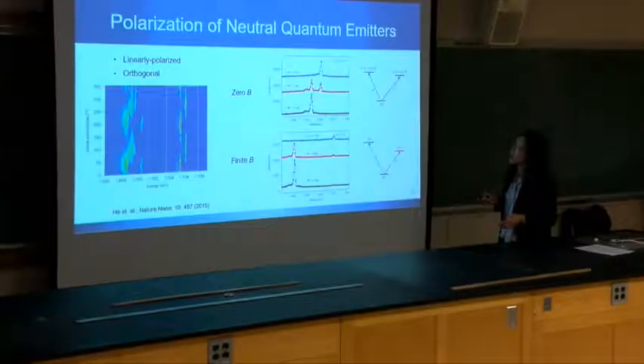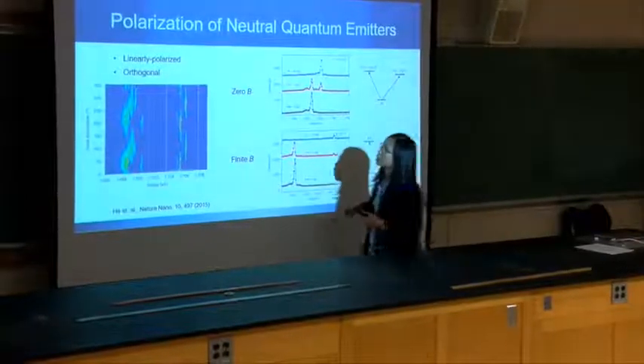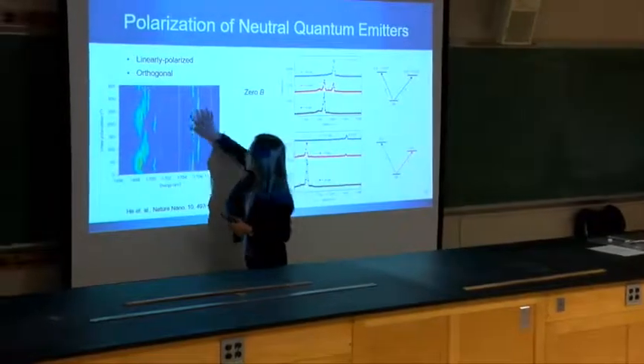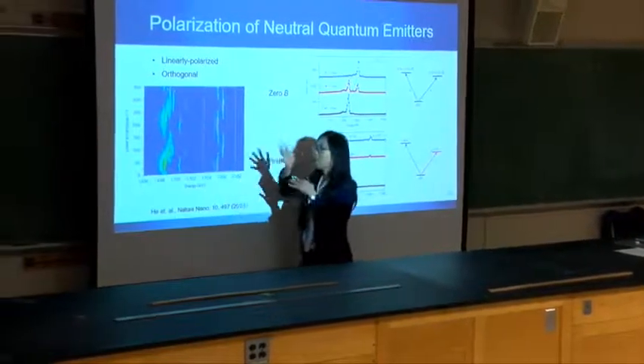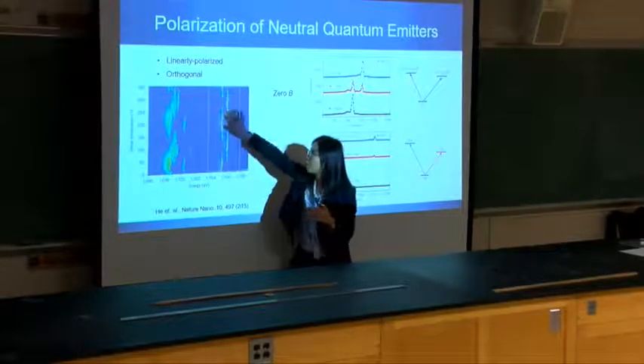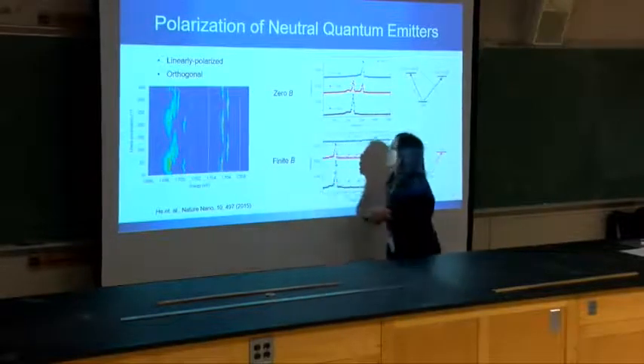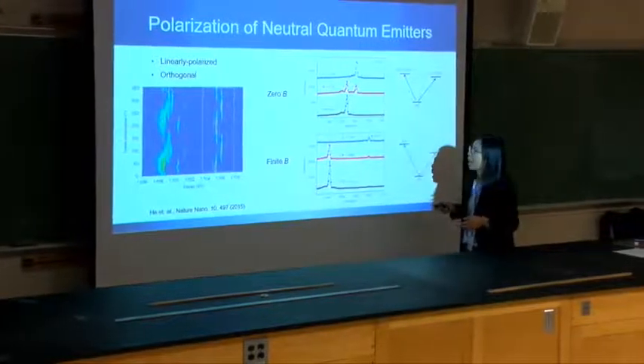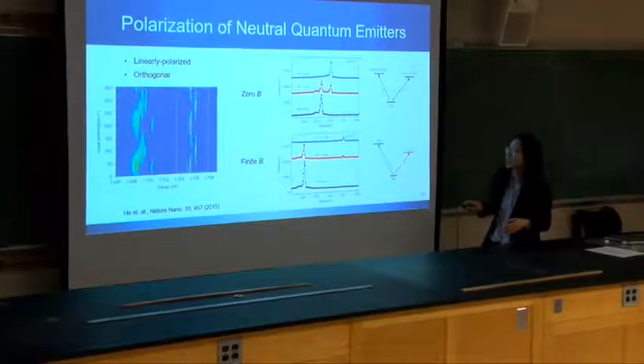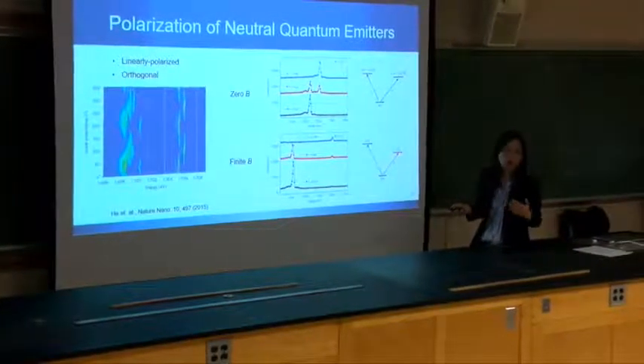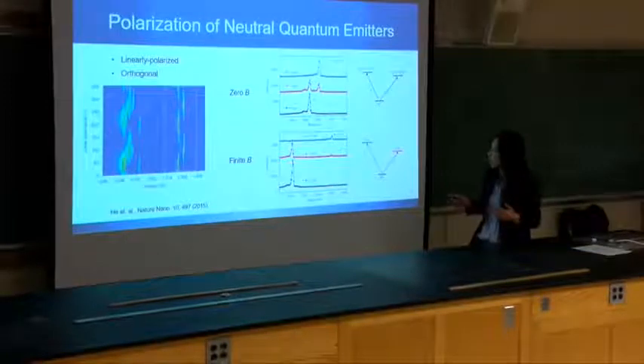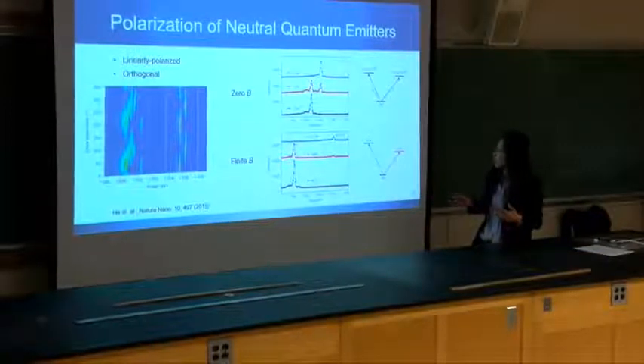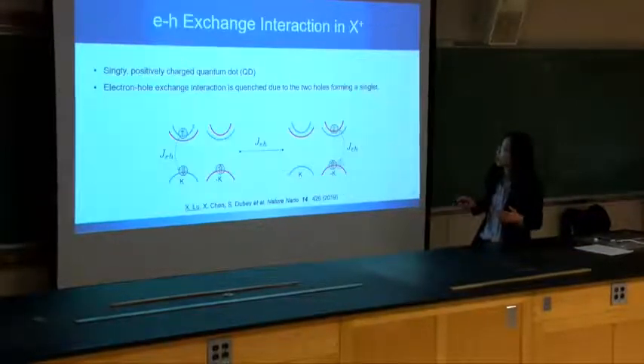And because of this fine structure splitting, the two peaks are linearly polarized, and their polarization angles are 90 degrees different. And if we apply a magnetic field to the system, and once it is large enough to overcome the exchange interaction, we can actually see the circular polarization restored.